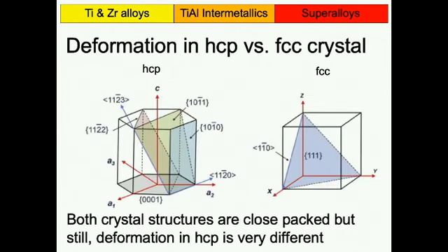This is very different from FCC. It is difficult to shear that crystal in all sorts of different directions. In FCC, your slip plane is 1, 1, 1. It's only one type, but think about all the different directions you can have 1, 1, 1 planes in that cubic cell. And the directions are 1, 1, 0, and there are three 1, 1, 0s here. You can reconstruct one by adding these two. You can really shear an FCC crystal in all sorts of different ways with 1, 1, 1 planes and 1, 1, 0 directions. What I'm trying to say is that if you only consider the easy slip planes, basal and prismatic, you don't have many ways of shearing that crystal.